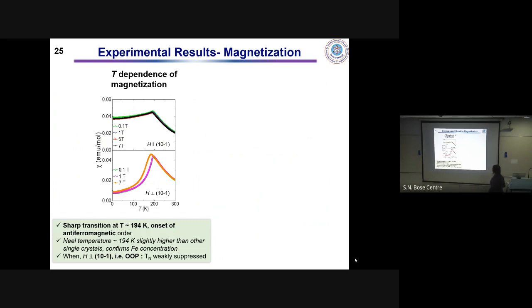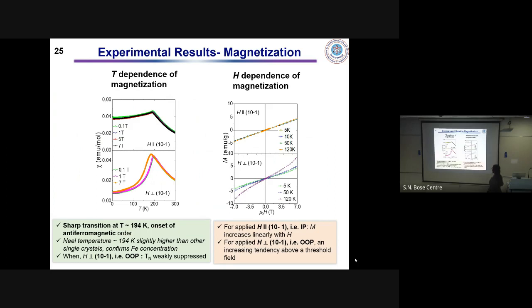So what we have observed is that when the magnetic field is applied perpendicular to this 1 0 -1, that's the out-of-plane direction, the Tn is weakly suppressed. From the field dependence of magnetization, when the magnetic field is applied in the plane, we see that M increases linearly with the applied magnetic field. This is common in the case of an antiferromagnet. However, when the magnetic field is applied perpendicular to 101, in the out-of-plane direction, for 5 Kelvin and 50 Kelvin, M increases linearly with H. However, when the temperature is close to 120 Kelvin, after a certain threshold magnetic field, there is a sudden increase of the magnetization.